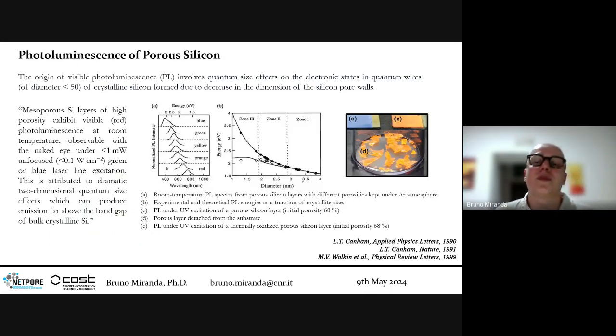As I said before, Canham was the first to discover the photoluminescence of porous silicon, and according to his measurements, the origin of visible photoluminescence is basically due to quantum size effects. So the lower the dimension of the features of the crystals created in the pore, the higher the photoluminescence.